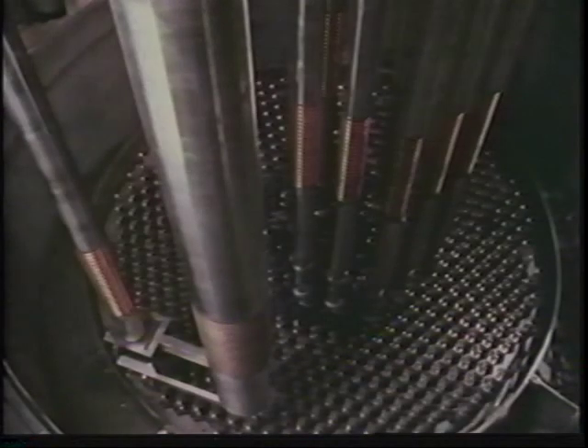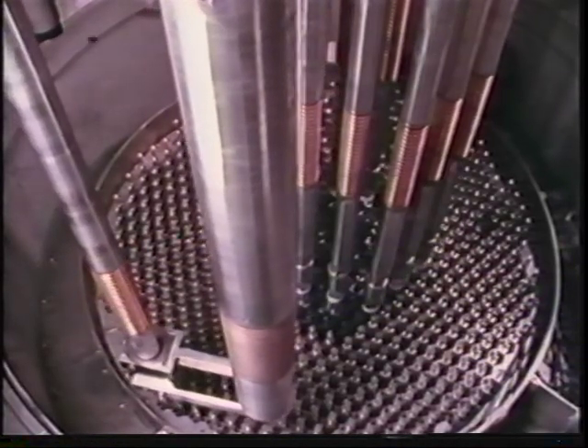By the time the swelling has reached the wall, the fuel is so spongy that further outward swelling is easily restrained by the cladding. High burn-up relies on adequate clearance. With metal fuels, the densities are high enough that the clearance can be provided, and nuclear performance surpasses that of ceramic fuel. Thousands of fuel elements irradiated in EBR-2 have been routinely discharged at 8.5 percent burn-up; many have exceeded 10 percent, and a few have attained 18.5 percent. New Mark IIa elements are expected to reach an average of 14 percent.